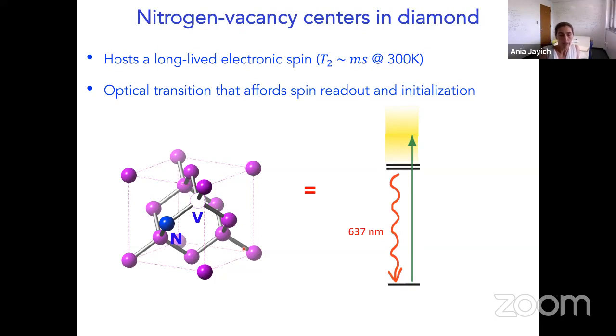Okay, so as a result of these favorable properties of the diamond lattice and the nature of the NV defect within that band gap of the diamond, NV centers can have very long, millisecond coherence times, even up to room temperature. Again, they have the benefit of being naturally trapped in a lattice. And it turns out that the optical transitions make it possible to easily see single spins.